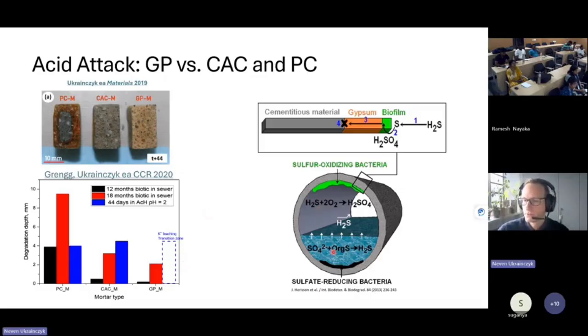So I will not go into the theory of this biogenic sulfuric attack, but basically you have the bacteria which eat the organic stuff, they thrive on it, and then they produce sulfide gas, which then builds up on top and then makes sulfuric acid, which of course is aggressive. You have the sulfate attack and you have acid attack, and this is a very aggressive environment where you need high performance materials.